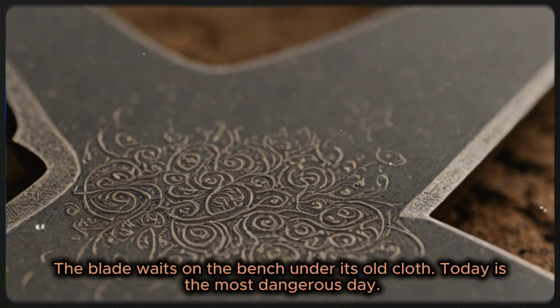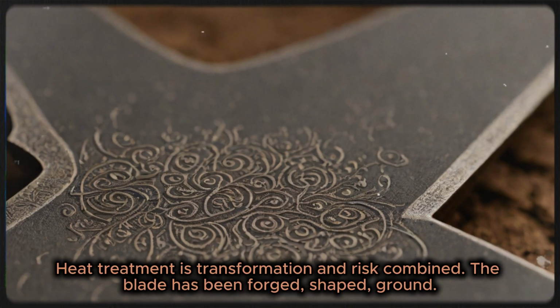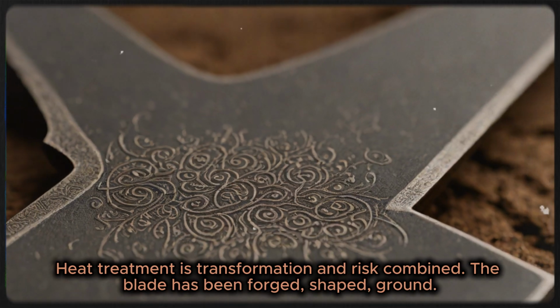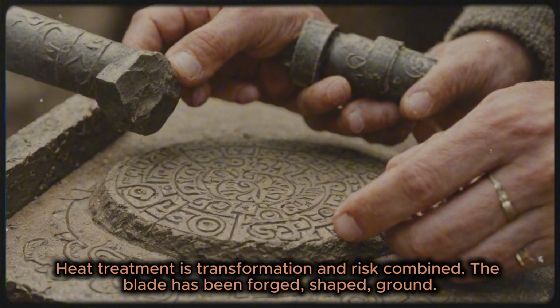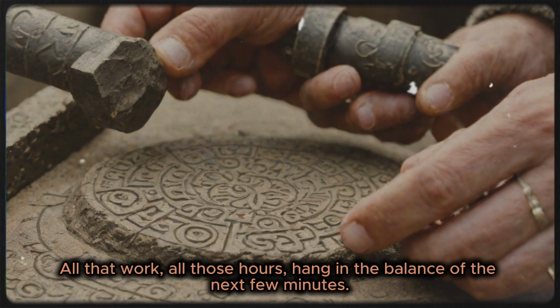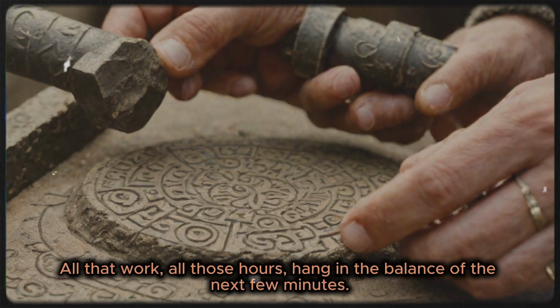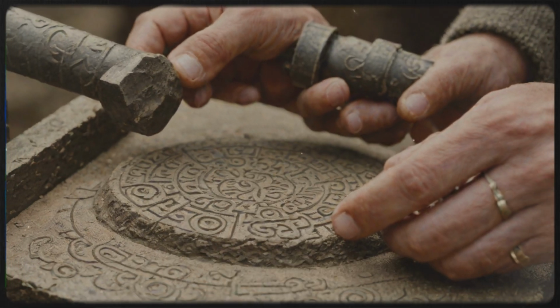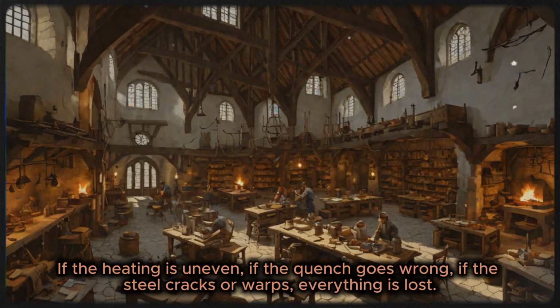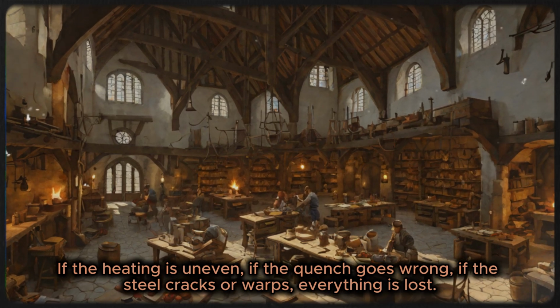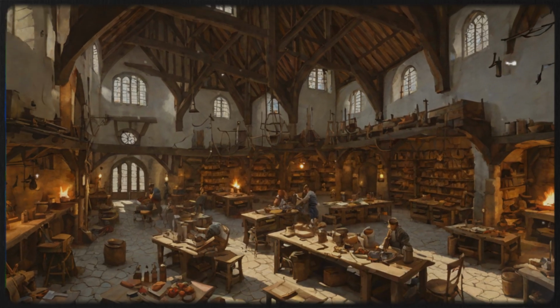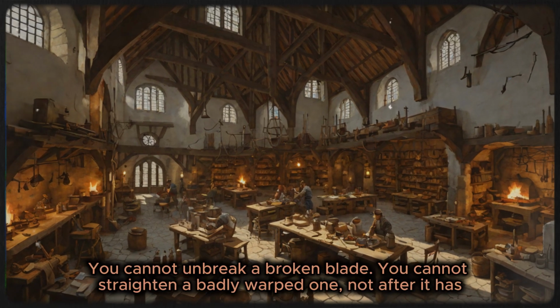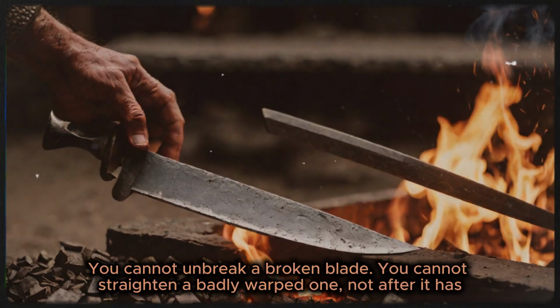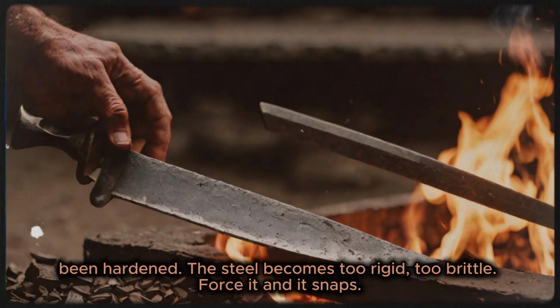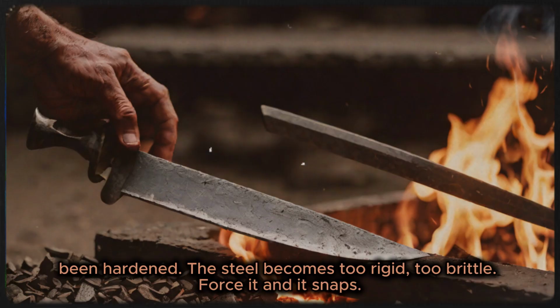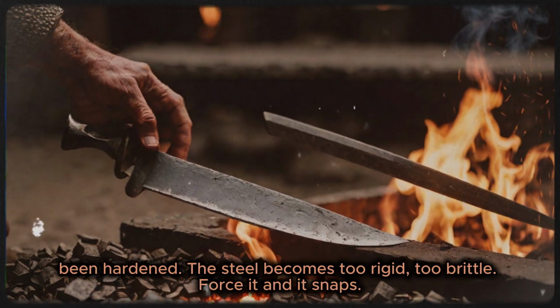Today is the most dangerous day. Heat treatment is transformation and risk combined. The blade has been forged, shaped, ground. All that work, all those hours, hang in the balance of the next few minutes. If the heating is uneven, if the quench goes wrong, if the steel cracks or warps, everything is lost. You cannot unbreak a broken blade. You cannot straighten a badly warped one, not after it has been hardened. The steel becomes too rigid, too brittle. Force it and it snaps.